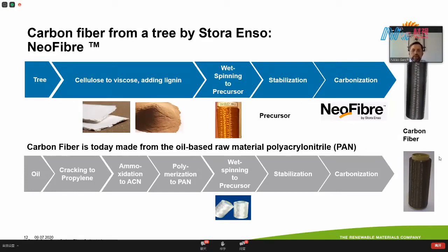Well, Stora Enso has a different approach. We start from the tree. From the tree, we obtain cellulose and lignin. The cellulose is converted to viscose. The viscose is then dissolved in caustic soda. And lignin is added to this mixture. And this is how the spinning dope is created. And this spinning dope can then be wet spun to a precursor. In our case, it's a brownish golden looking precursor reel. And this precursor is spun in a similar method as viscose fibers are spun today. The precursor reel is then subjected to thermal treatments in stabilization and carbonization to give our neofiber, our novel carbon fiber. So you can see that practically industrial unit operations are being used for making the precursor and the carbon fiber.